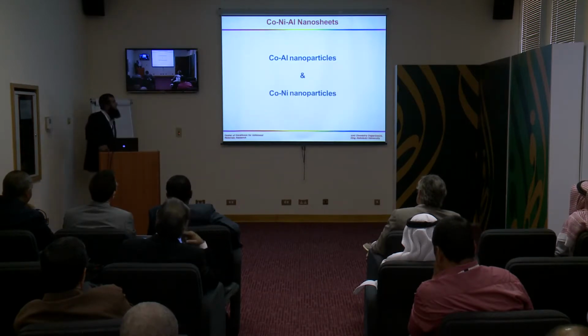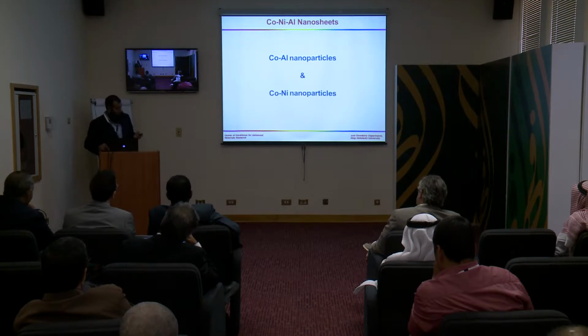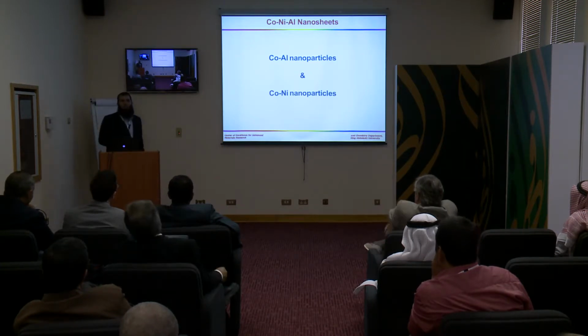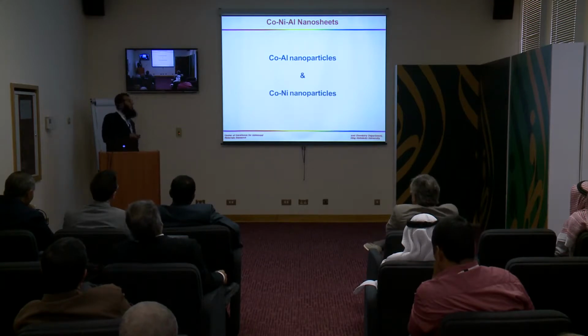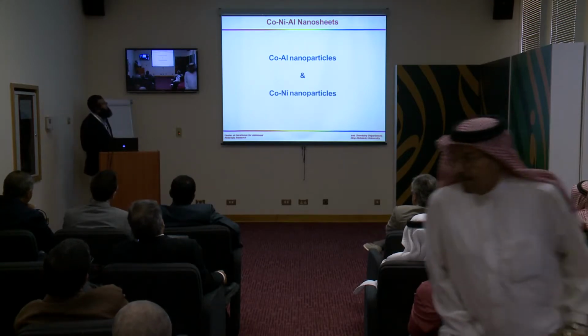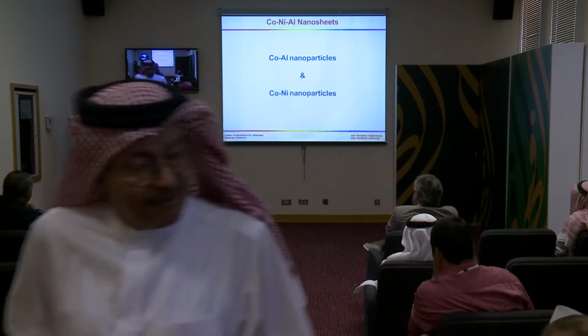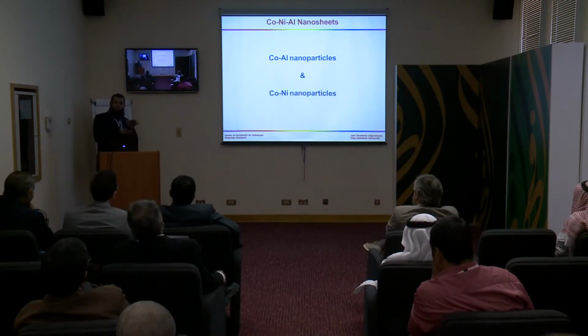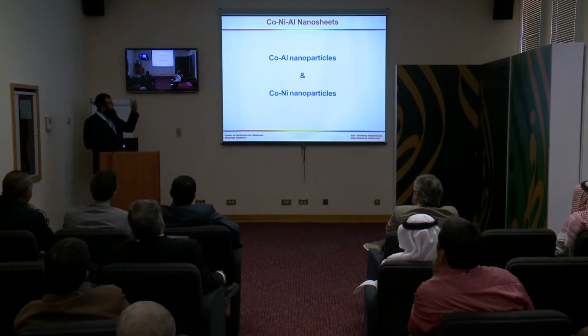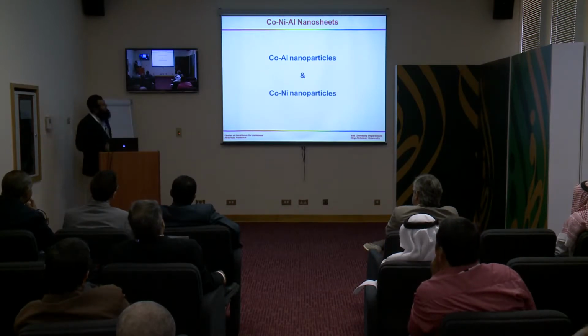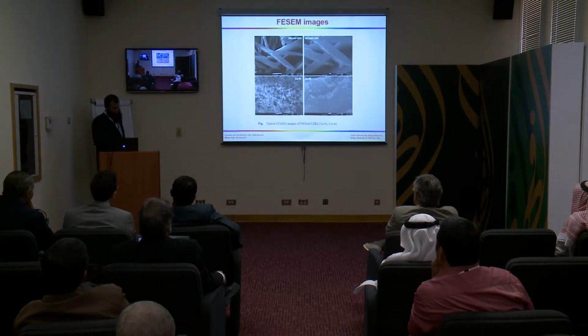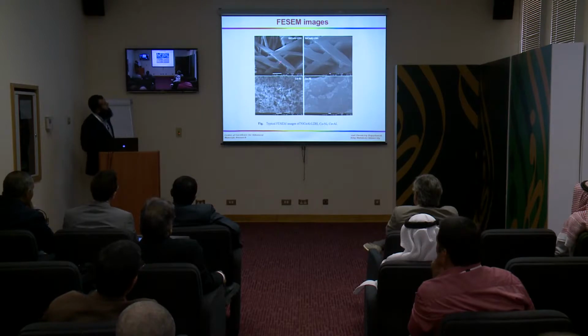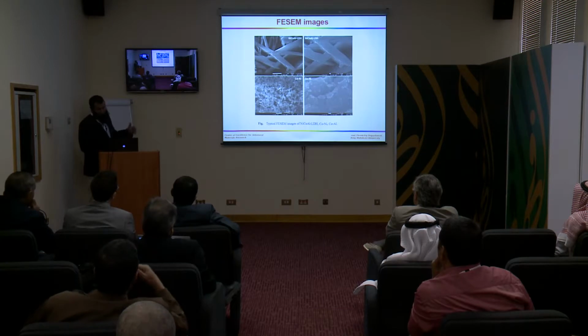Then we checked another combination, because there is a lot of literature which shows nickel and manganese as good candidates for water splitting. So we made a combination of cobalt, nickel, and aluminum, and when we synthesized the material, it was in the form of LDH. We compared this LDH with cobalt aluminum nanoparticles and cobalt nickel nanoparticles. The LDH showed a sheet-like structure, but the other materials showed nanoparticles.